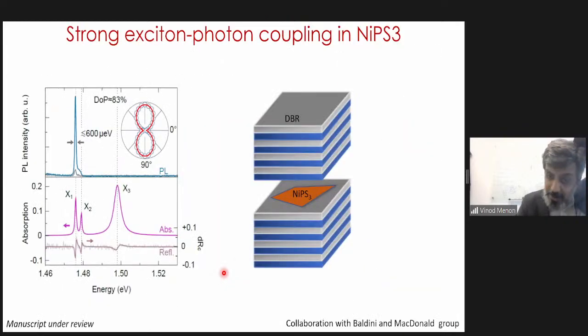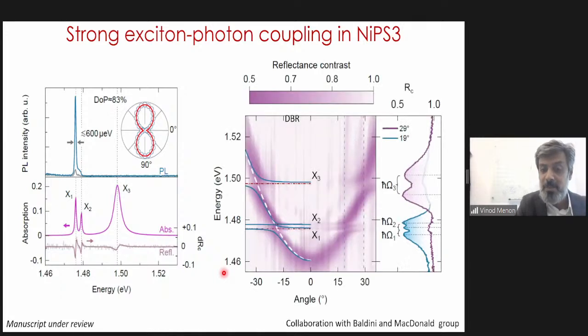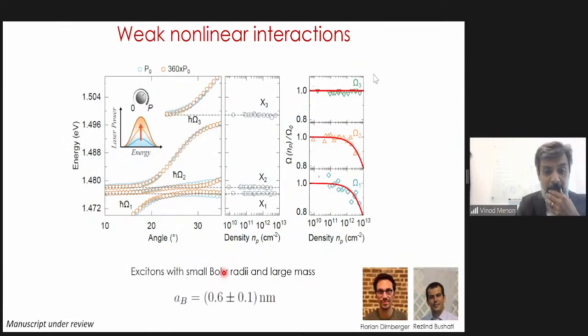And in fact, this paper just got accepted and should be coming out soon, where we showed that we can get strong coupling in the system, but more importantly, we were able to shed some light on the nature of excitons. So here is an example where we took a correlated material. We did not understand much about the nature of the excitons. And then we used strong coupling as a means to study those things, because they couple to photons, we can interact, we can probe them more easily, and we were able to understand a little bit more about the nature of the excitons. Again, this work led by Florian and my grad student Reslan.